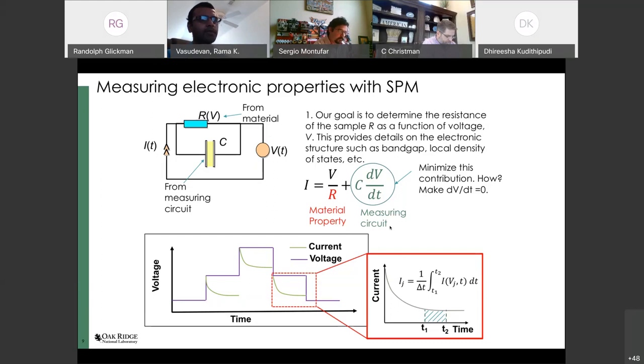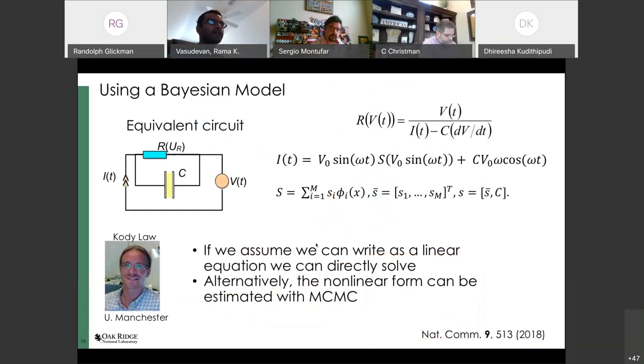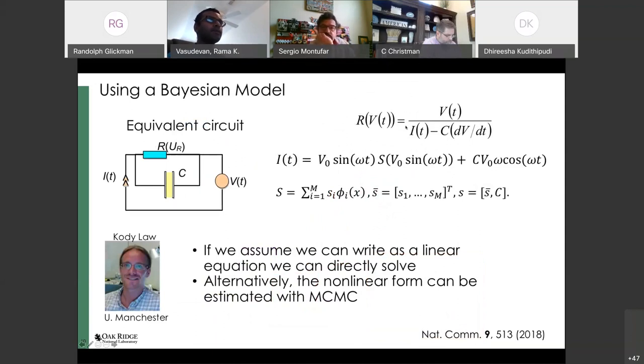We asked: instead of applying a DC voltage, what if we apply an AC voltage at some particular frequency? It turns out you can. If we have a sinusoidal voltage, we can rewrite the circuit equation as a linear sum with basis functions. Given that we know the model of the circuit, we should be able to infer the capacitor's contributions from the data itself — making this a Bayesian inference problem.